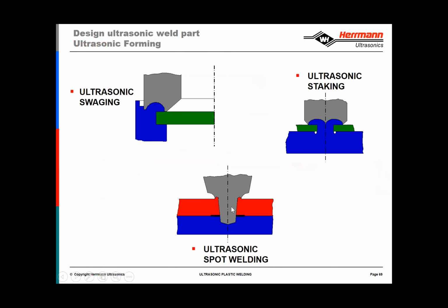This results in a sort of rivet head being seen after the welding, and it's often done on thermoformed parts or parts that you cannot usually weld with an energy director, or very large parts that don't require a full perimeter seal, but rather might just require some spots to be welded.